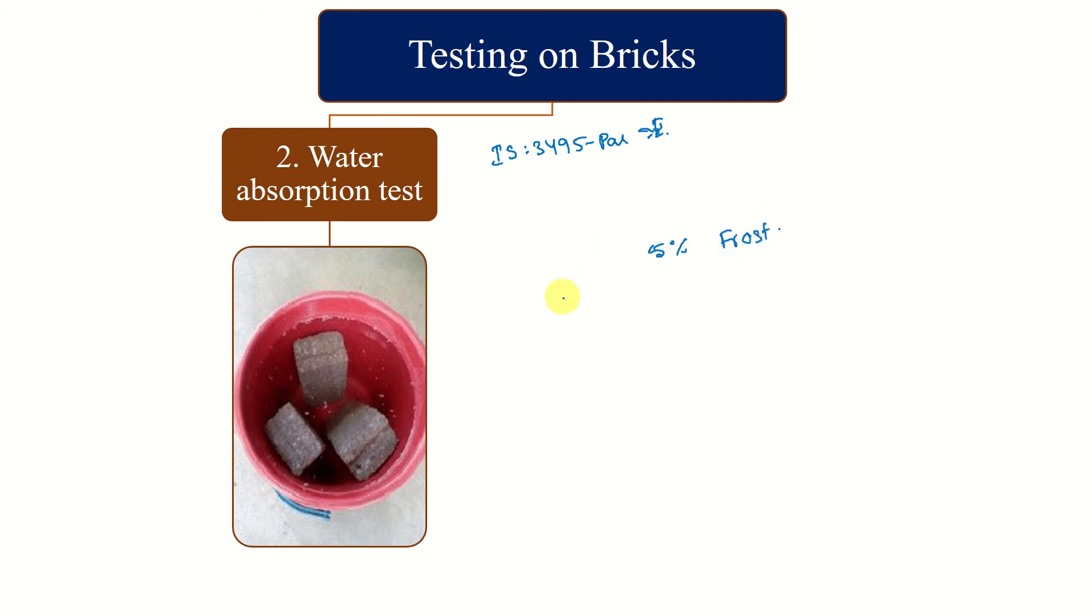It has been reported that if water absorption is less than 5%, the effect of frost is negligible. The water absorbed by the brick from rain is stored in pores. As temperature goes down, water retained in the pores will freeze and may create cracks. The obvious reason is that frozen water has more volume compared to liquid state.